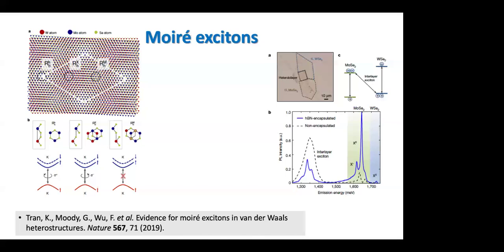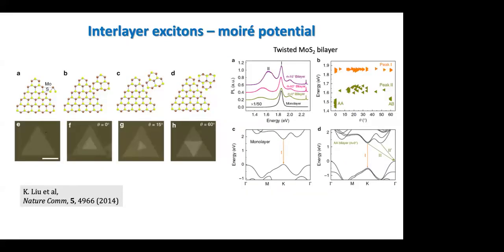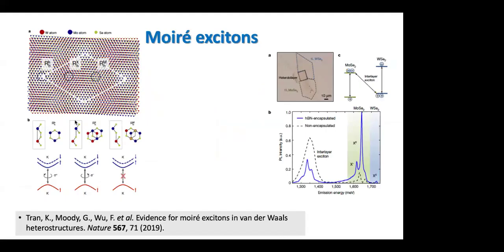And finally, the idea of so-called moire excitons. Moire potential, what does it mean, moire potential? If you look at two layers of fabric, very tightly woven fabric, sometimes you can see what we call a moire pattern. And this works also for those materials. If you look at the positions of atoms in two layers of TMD, which are put one on top of the other, you can see that depending on the place, that arrangement is different. You can see the moire pattern, moire exciton, moire potential, which localizes excitons. Completely new stories.